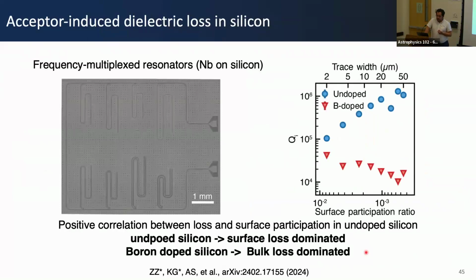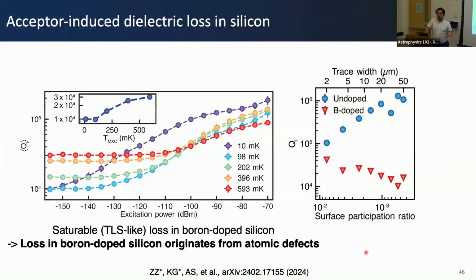So to test these, we made some resonators. And what we find is that in undoped silicon, our losses are dominated by surface losses, the amorphous. But if we dope the silicon, our losses are dominated by bulk. And the losses we get from bulk, they're not just some resistive loss. It actually follows the saturable absorber response that you expect from a two-level system. So as we increase the microwave power, the Q improves because they saturate and they can't absorb any more power. So basically, these borons in silicon are showing all signatures of a two-level system. Their temperature dependence also shows the saturation response you would expect.